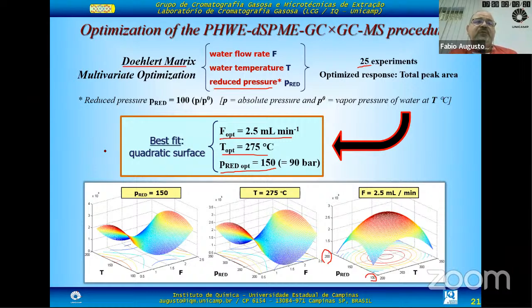Most of the works of Professor Psillakis are performed on aqueous samples. In those cases, she used, in some cases, sodium chloride to displace the equilibrium. It makes sense, but in our case, no. If we added solid sodium chloride there would be no effect, because the sodium chloride would stay in solid state, and the sample is in solid state. It's not a solution. And if we add water there, we would have problems with the evaporation of water, breaking the vacuum, making the vacuum more difficult to apply. So in this case, we don't use sodium chloride as opposed to most of the operations using headspace solid phase microextraction.